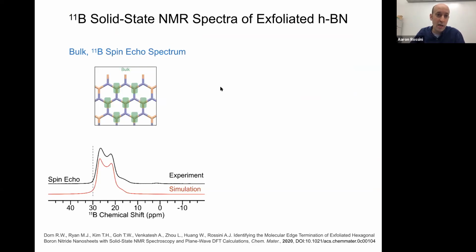Okay, what about boron? Boron 11 is also a really good nucleus for NMR spectroscopy. It's got a natural abundance of about 80%, pretty high Larmor frequency. It would be 128 megahertz on a 9.4 Tesla spectrometer. So if we just do a boron spin echo, we're mainly going to see the NMR signals from the boron atoms in the interior of the sheets, the bulk-like boron atoms, because that's going to make up 99% of the sample. And we get this characteristic second order magic angle spinning quadrupolar powder pattern here.